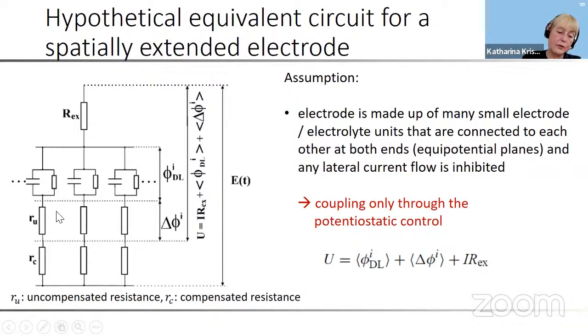So we have an equivalent circuit as shown here, where one of these units is composed of the interfacial circuit, and now I divide the electrolyte resistance between the working electrode and the counter electrode into a compensated part and an uncompensated part. So my reference electrode would be at this point, and I assume that the reference electrode has the same distance to all positions of the electrode, which is hypothetical for most electrode geometries, but you might realize it, for example, with a ring-shaped electrode, where you put the reference electrode on the axis of the ring.